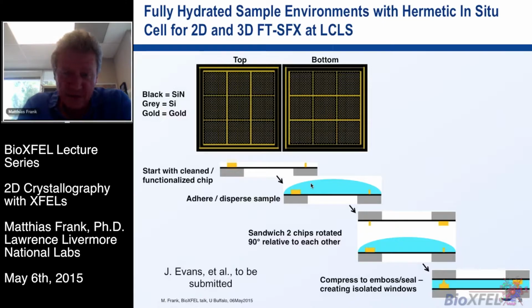I did not talk much about the vacuum protection, but for the 3D crystallography, you can, for example, embed your microcrystals in something that is vacuum protecting, like an oil, and it has to be an oil that's approved by the beamline, so it can't be any oil. They don't like certain oils in the vacuum chamber, but Paratone-N is one of the oils that we're allowed to use, and that works very well.